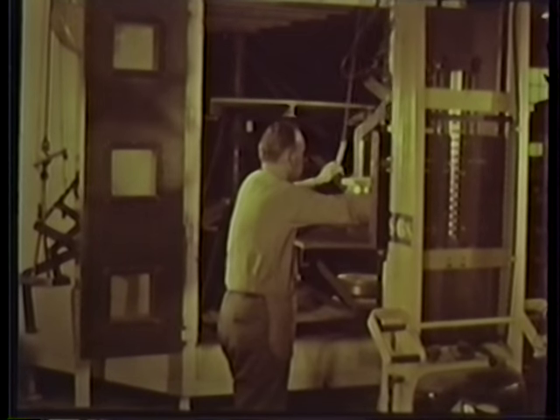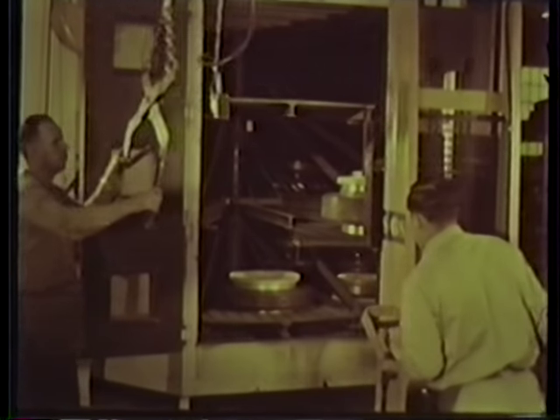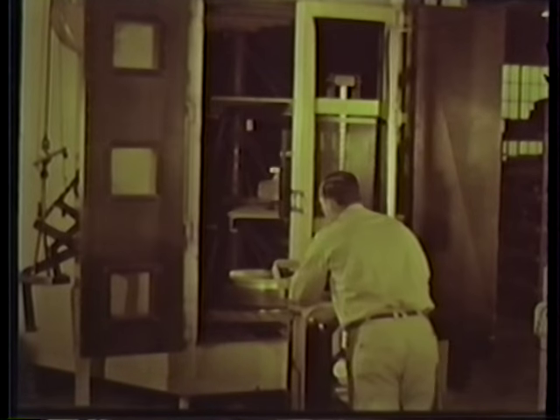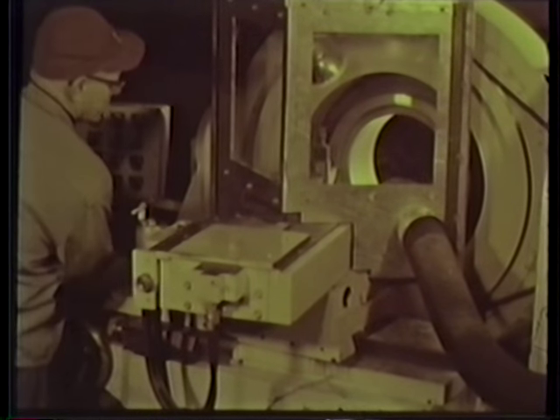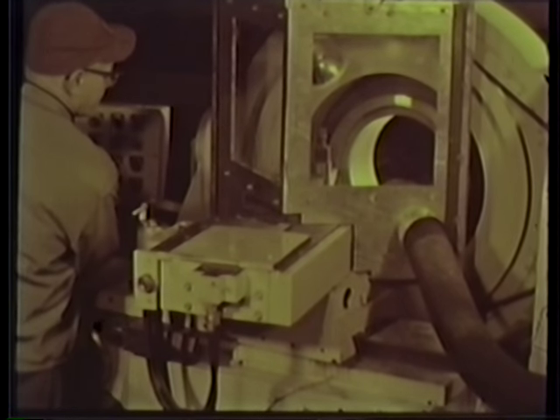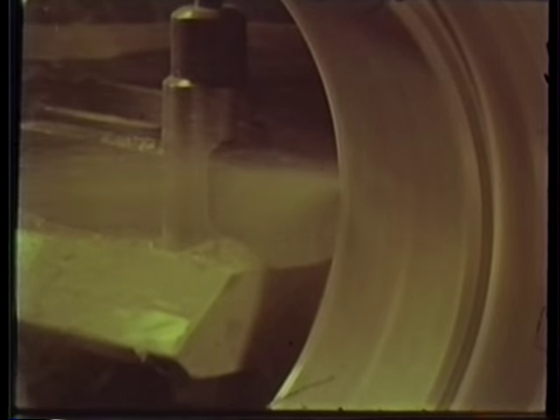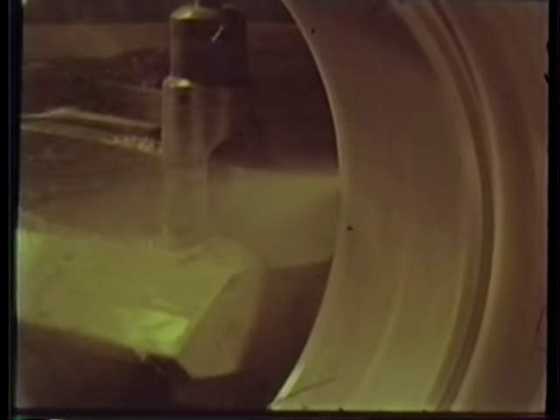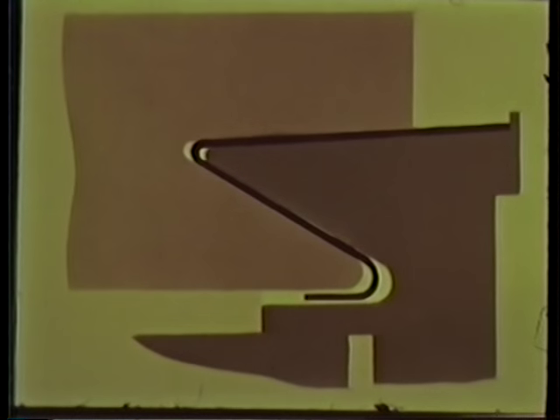After an initial press, some commutators are given a short oven treatment to develop dimensional stability. Others bypass this first bake and go directly to the boring lathe, where the brush end is faced off and the V-bore is machined. This step must be precise, regardless of whether the commutator is to be of the V-bound type or of the arch-bound type. With the V-bound commutator, most of the pressure from the cap and shell is carried on the 30-degree surface. But the amount carried on the 3-degree surface is very critical. Either too much or too little pressure at this point will cause roughness in the overhang area.